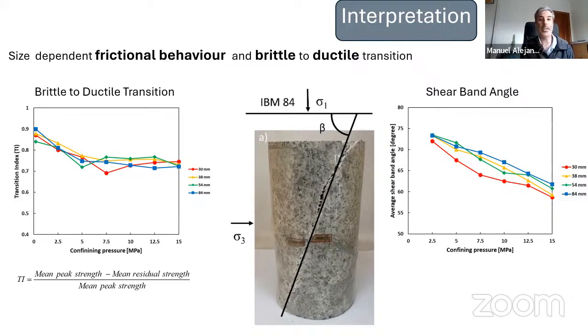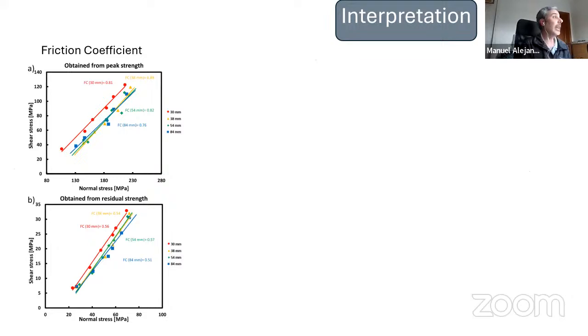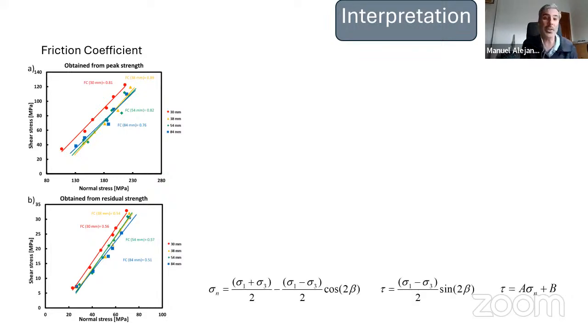Clearly, the shear angles near 0 confinement pressure were impossible to measure. And we observe for all the diameters used that the shear band angle decreases with the increasing of the confining pressure. So with this data and with the expression of the shear stress and the normal stress, we can plot the friction coefficient both for the peak and the residual strength. So we can obtain the values for each diameter.